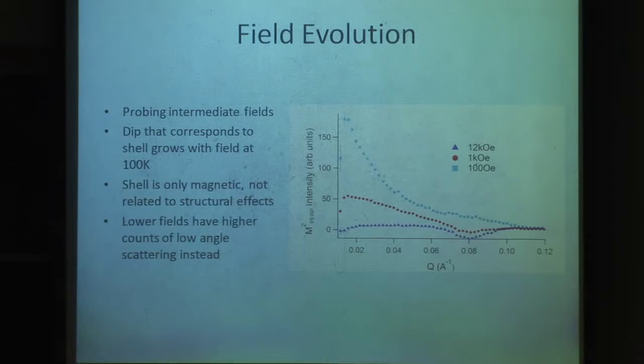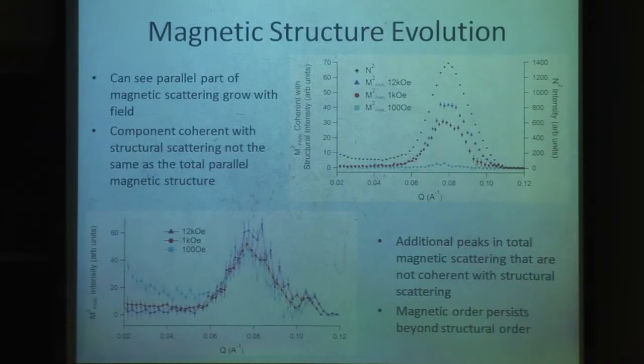We don't have it at all in the structural data, but it's only a magnetic shell. We've also found that when we get to lower fields, we have a lot more scattering here in our lower Q region, which is that lower angle. I've also been taking a look at how to extract the parallel scattering in different ways and what effect that has. We've seen that the parallel scattering grows as we increase the field. Here our low field again, and our intermediate field, and our high field have different intensities.